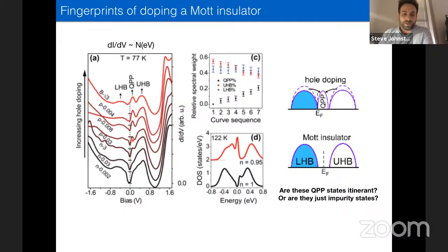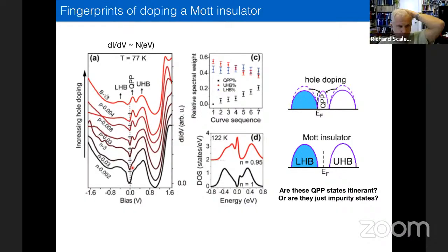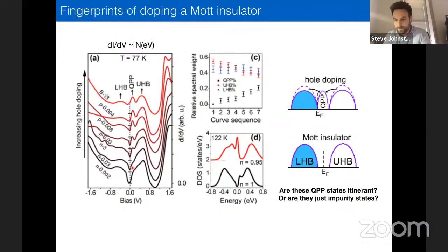And so the next thing we wanted to check is, is the system actually dispersive? Now, the immediate thing that leaps to mind is to do photoemission, right? You can do an ARPES experiment and try to measure a dispersive band. The problem is that in these doped systems, you can't grow films or monolayers of sufficient size to really do an ARPES measurement. They're on the borderline of nano-ARPES, but they're not quite big enough in order to do a photoemission experiment.